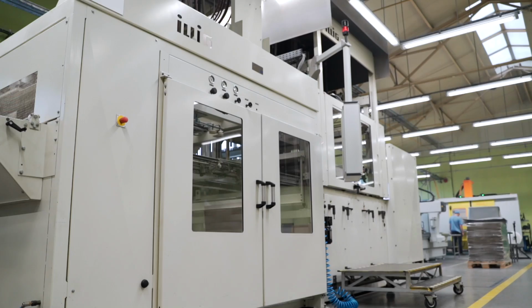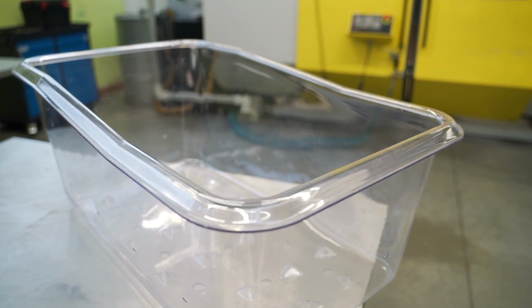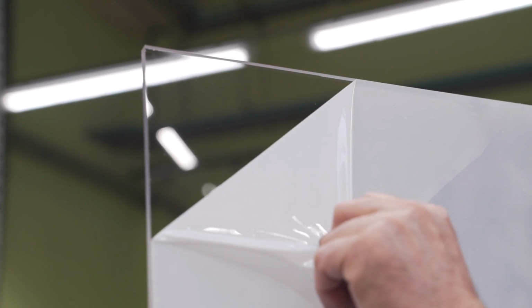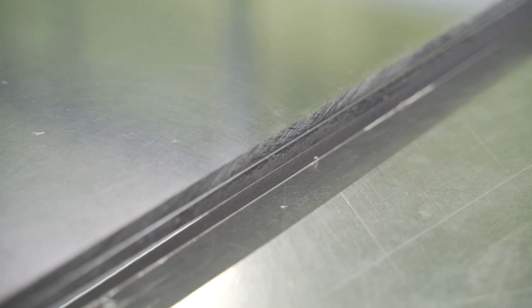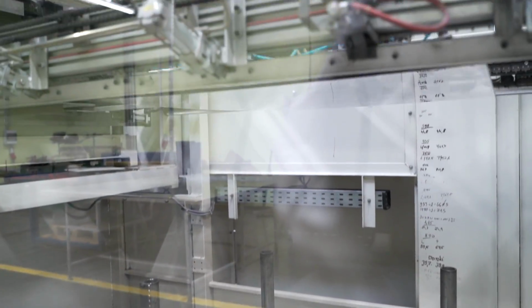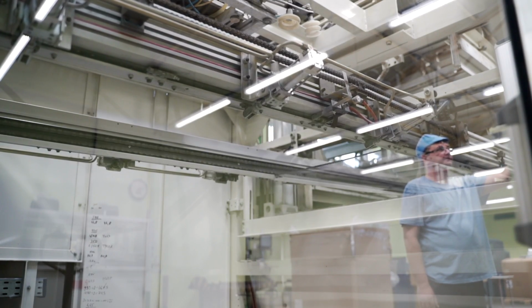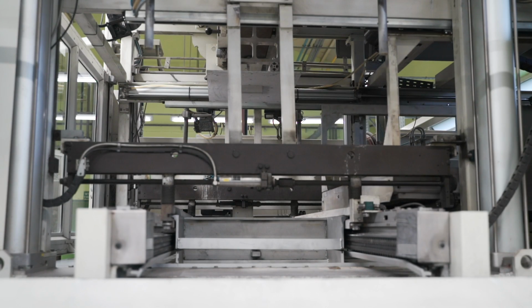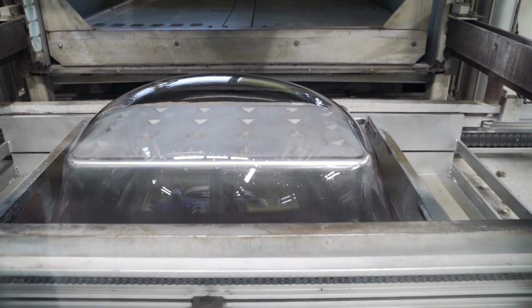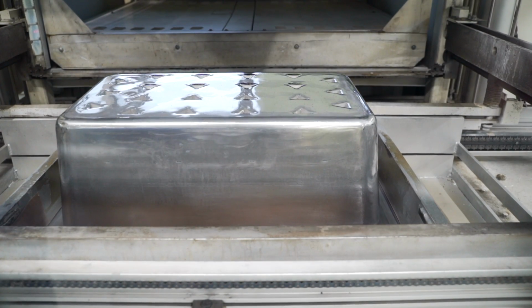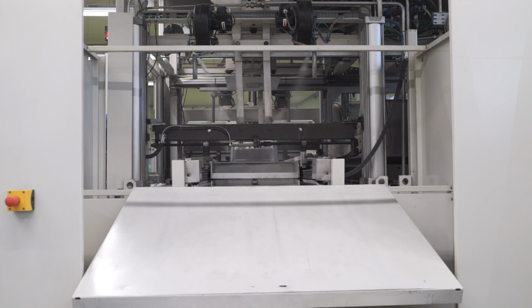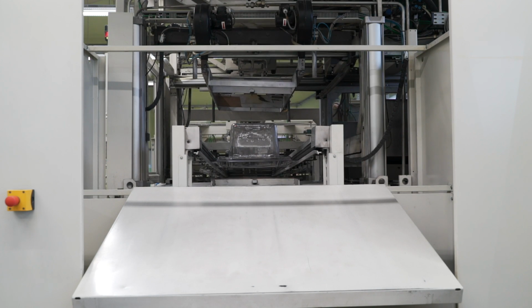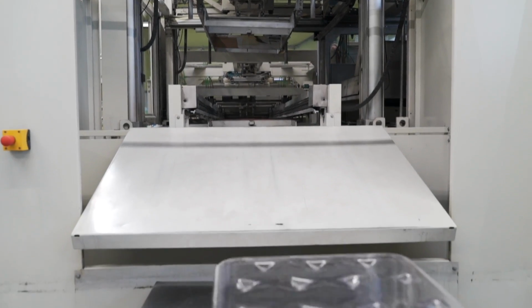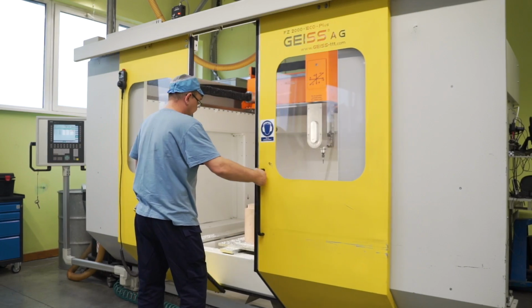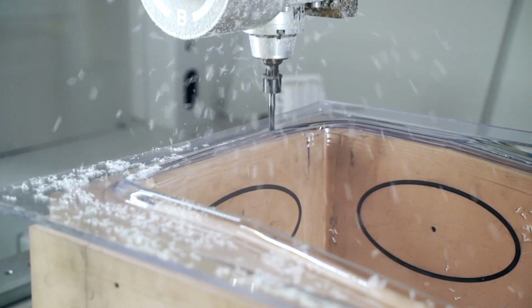The moment of forming of the product is clearly visible in machines which produce large-sized thermoformed elements. The product is made of polycarbonate cut sheet of about 8 mm thickness. The raw material has high transparency, just like glass. The cut sheet is heated on both sides. Then, with a blow, the flexible material is vacuum sucked into the mold. On a cold form, the material stabilizes. Cooling takes about 180 seconds. After collection from the line, the CNC machine cuts off the excess and mills the edges.